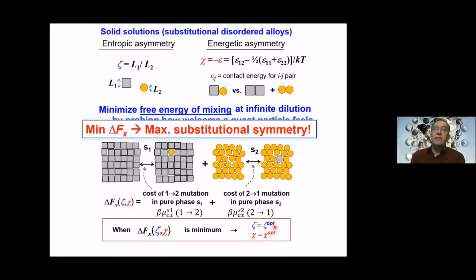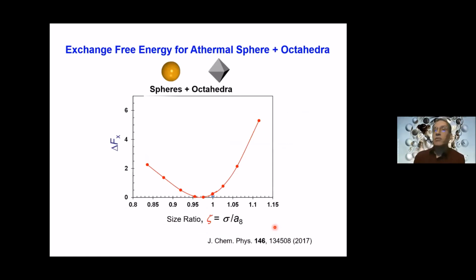And the idea then is that that will maximize the substitutional symmetry of the two components. So let's see how that works for the example I showed you of spheres in octahedra in this athermal mixture. This is this delta Fx as a function of the size ratio, the ratio of the diameter of the sphere over the octahedral edge. And it clearly shows that there is a minimum there for a value of zeta of about 0.96, which is different from the one I showed you before. Now this equal ODP happens to be over here.